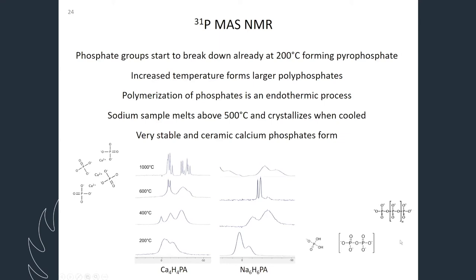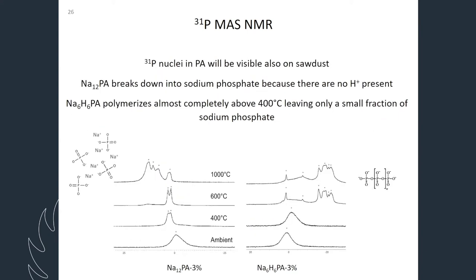And at 1000 degrees, the calcium is very, very crystalline. But the sodium sample has melted, and then it has lost all its crystallinity when it's condensed again. So those ceramic calcium phosphates that have formed, they are very stable at 1000 degrees. That's what is left from the flame retardant. The carbon part is gone, and we have the calcium phosphate or sodium polyphosphate and calcium polyphosphates in the mixture.